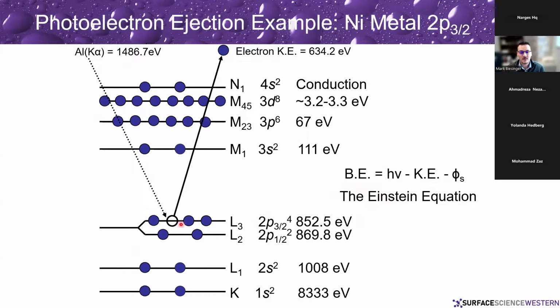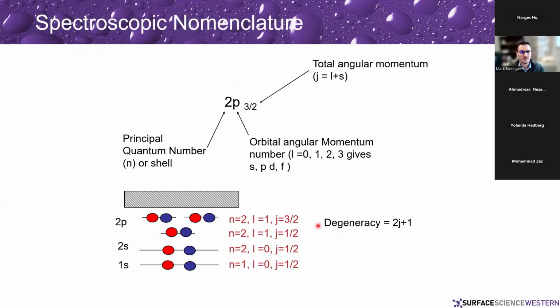Shine that at a nickel sample, it kicks out a photoelectron. The kinetic energy is 634.2 eV for a 2p3/2 photoelectron. You can then calculate that back to be 852.5 eV binding energy. Spectroscopic nomenclature follows these rules. So you have your principal quantum number of 2, orbital angular momentum, total angular momentum to define what orbital the photoelectron comes from.